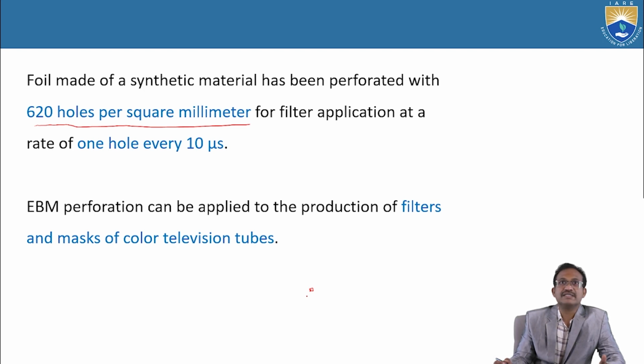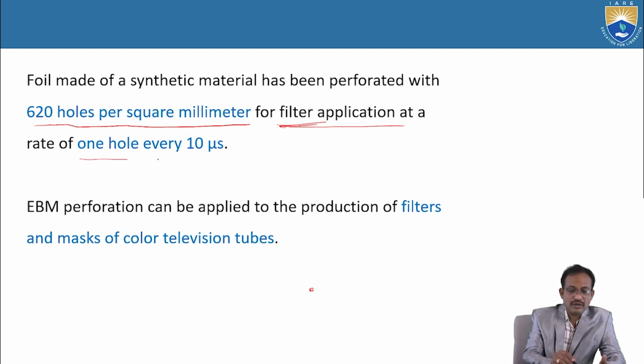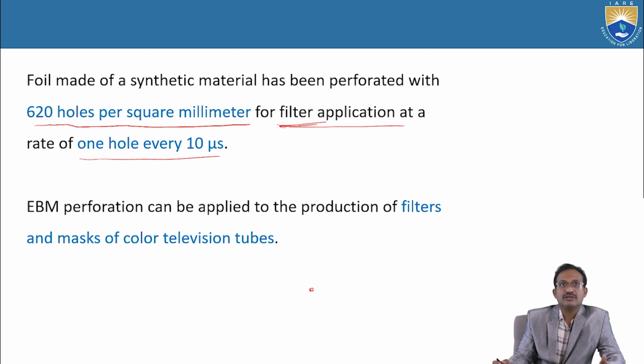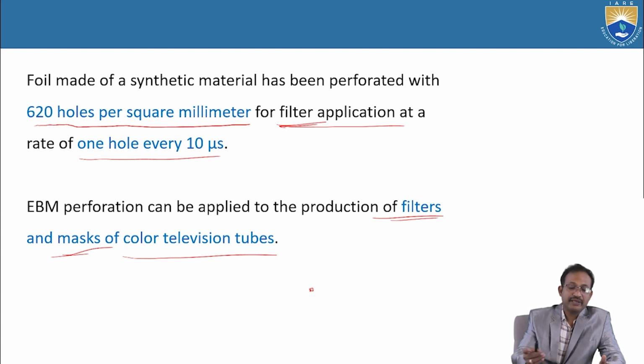Foil made of a synthetic material has been perforated with 620 holes per square millimeter for filter application. So here the application is filtering, at a rate of 1 hole every 10 microseconds. So in 10 microseconds, 1 hole will be produced. EBM perforation can be applied to the production of filters and masks of color television tubes. So for color TV tubes, filters and masks are produced with this EBM perforation.